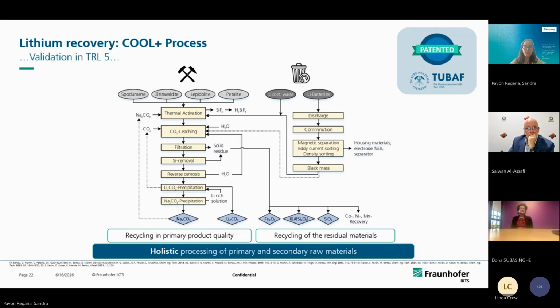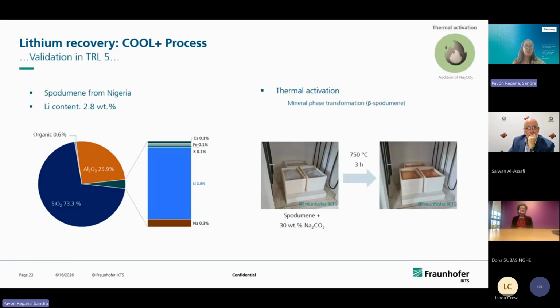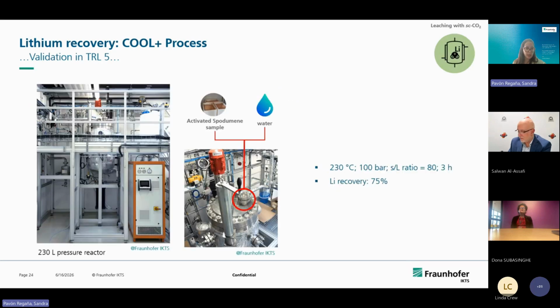precipitation. So what we have been doing for the last 3 years: we got spodumene from Nigeria, with a lithium content around 3%. We start with the thermal activation, adding sodium carbonate. And then we could decrease the temperature from 1,100 degrees to 750 through 3 hours. And then we already have beta spodumene that can be processed directly through our reactor.